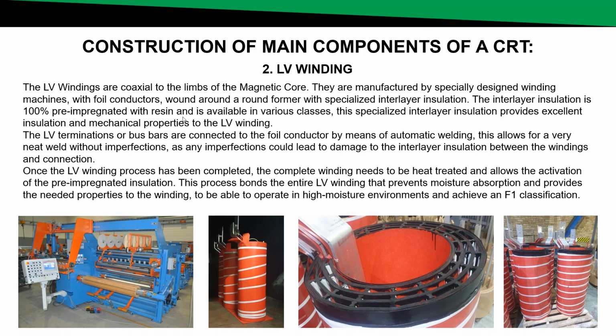By using this type of configuration for your LV winding, it also provides the LV winding with excellent insulation and mechanical properties. For the LV terminations or busbars that need to be welded onto the actual foil of the LV winding, an automatic welding machine is used. This ensures that there are no imperfections or sharp edges on that weld, which could lead to interlayer insulation failure due to the stresses of the transformer during normal operations.